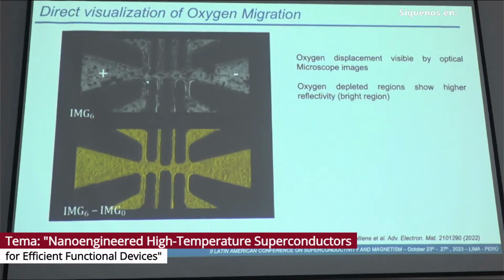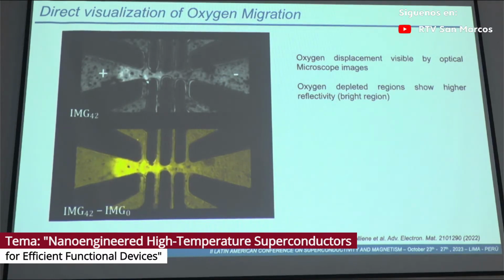And in this video here, what we can see is the change in the brightness of the image when we change the oxygen content, when we apply voltage that drifts the oxygen vacancies in this direction and then come back and drift the oxygen vacancies to the other direction.